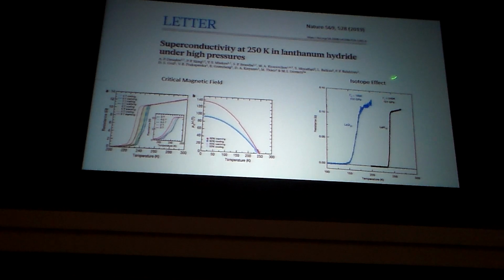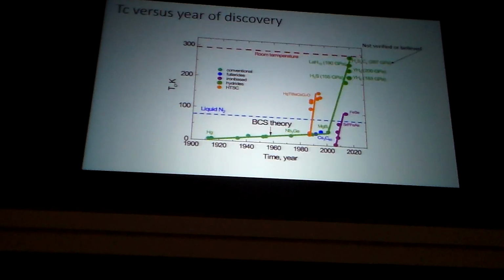So the more recent one, 2019, lanthanum hydride, which is basically lanthanum with 10 hydrogens, can be stabilized under high pressure and then measured. And again, superconductivity was found at even higher temperature. Here's the isotope effect. Here's the critical field data. And at least 2 groups have done this. So I think this work is quite believable. Okay. So now we have a new TC versus time picture. Here are our cuprates, but now we have these compressed hydrogen-containing compounds. So I would say this is a very exciting area of research now.